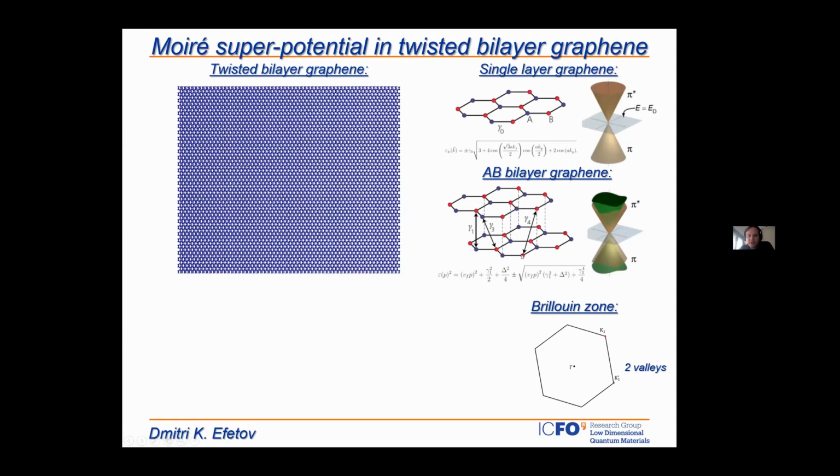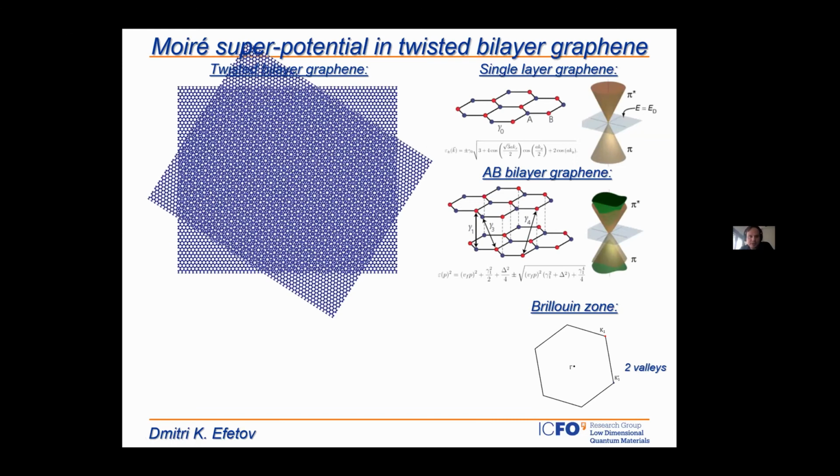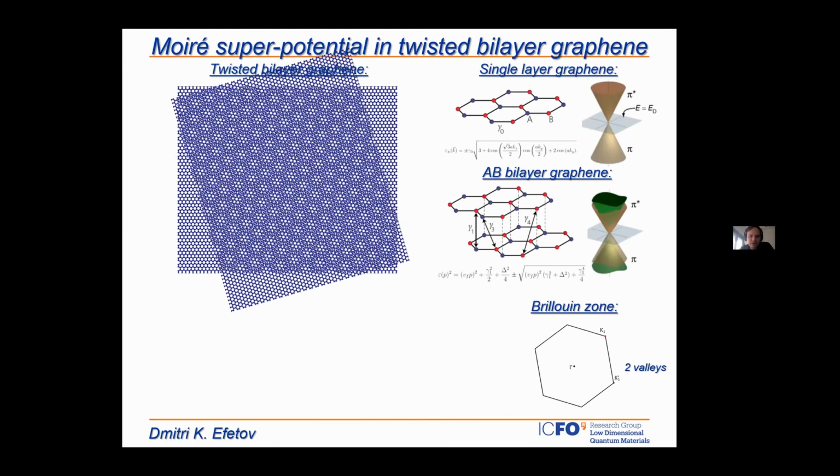Because we now have many additional hopping terms between the layers, the dispersion relation becomes renormalized, and instead of a linear dispersion relation we get a hyperbolic dispersion relation, which is almost quadratic at zero energy. Of course, all these hopping terms get mixed up when we start changing the orientation of the crystal. This is what happens if we twist one layer on top of another.